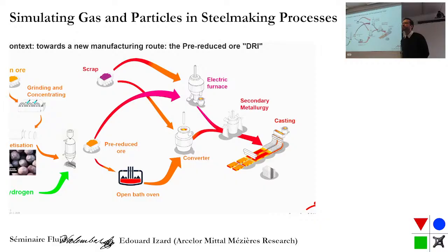Did you check that if you impose your gas flow, maybe you did not need cohesion? No, we need cohesion. It's the first thing we have done, but we have seen nothing, only a small recirculating part. Due to the charging, at the very beginning, it's very dense, so the first collapse plays a role. Then it's better to impose the first cavity because it will aerate the media a little bit close to the injector. This is why we have done it this way.